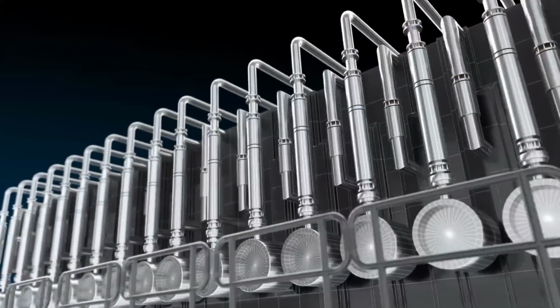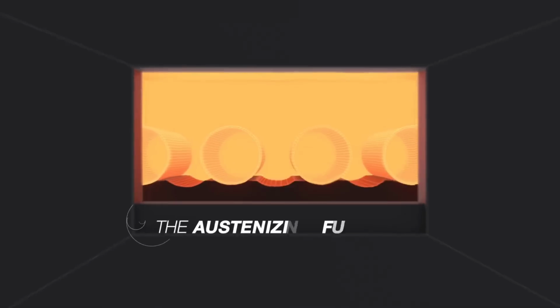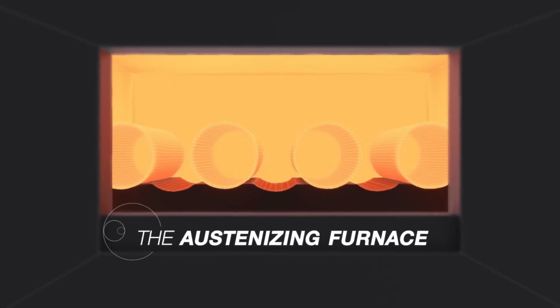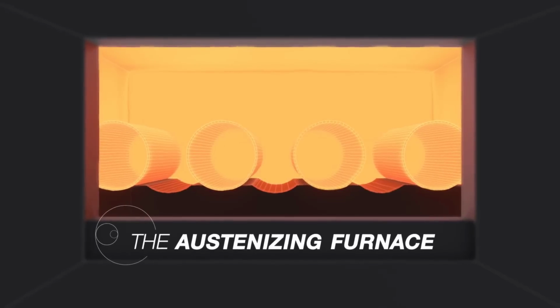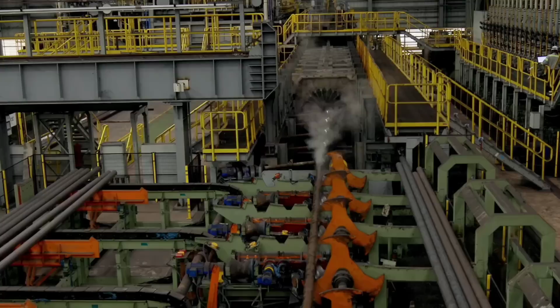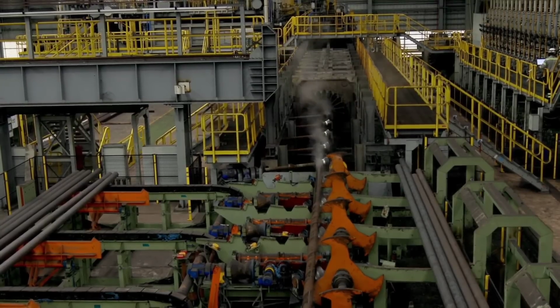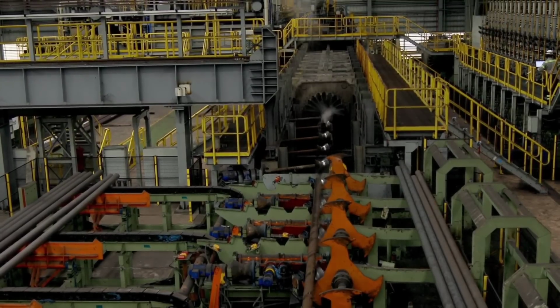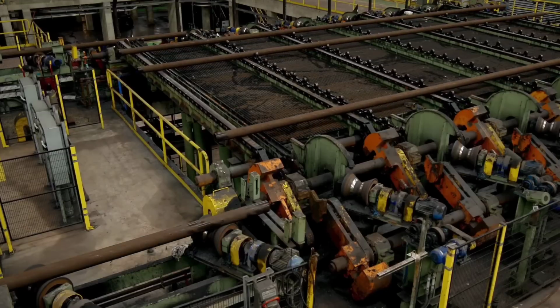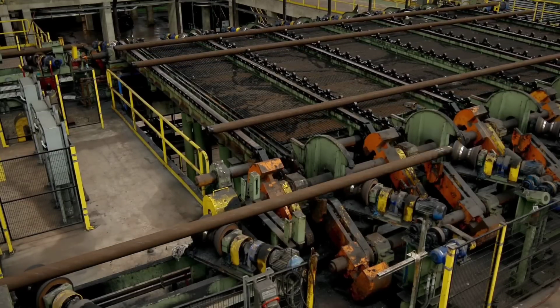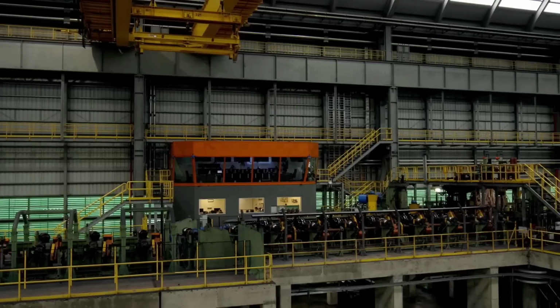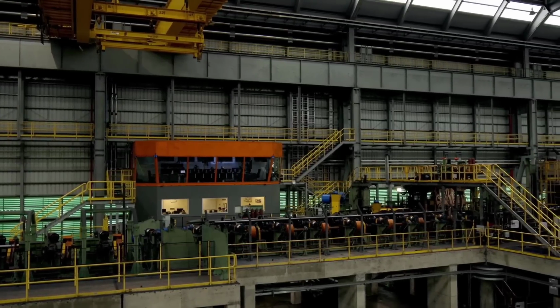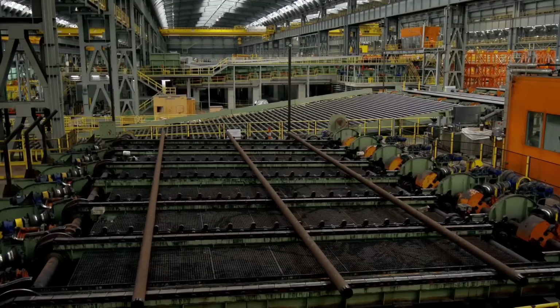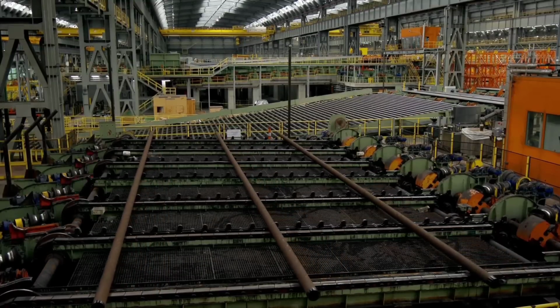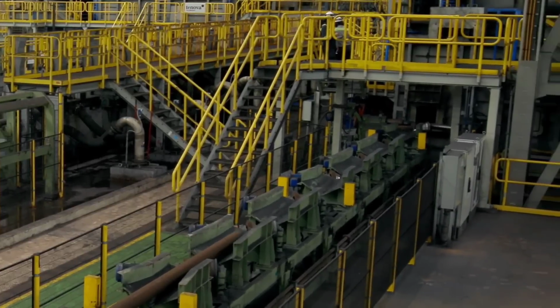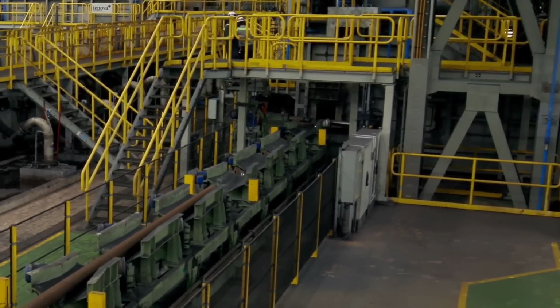Ensuring the hardness and toughness of the steel pipe is crucial, and this is achieved through the heat treatment process. It starts in the austenitizing furnace, where the pipe is reheated above the austenite transformation temperature. The pipe then enters the quenching process, where water sprays rapidly cool it from approximately 900 degrees Celsius to ambient temperature. This rapid cooling causes a phase transformation in the steel, resulting in a very strong but brittle martensitic phase.